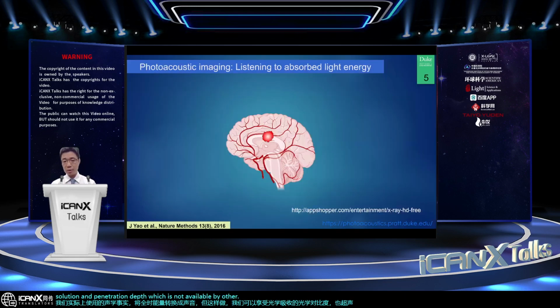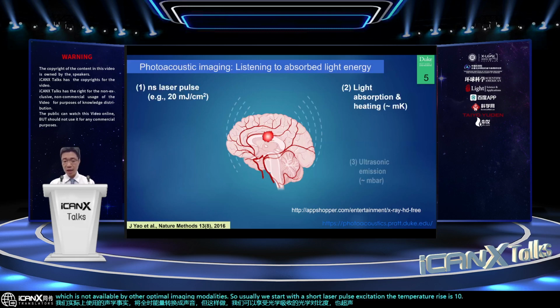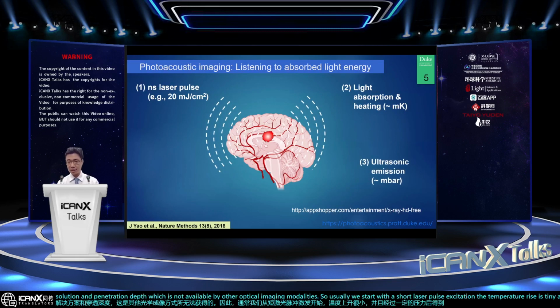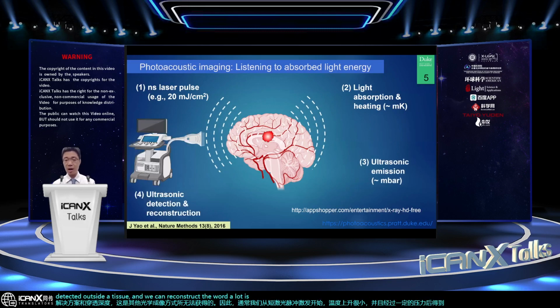So usually we start with a short laser pulse excitation, the temperature rises tiny, and we get ultrasound pressure, which is detected outside the tissue, and we can reconstruct where the light is absorbed, and so we can recover the optical absorption contrast. While the signal is carried by ultrasound, we can enjoy the ultrasound penetration and resolution.